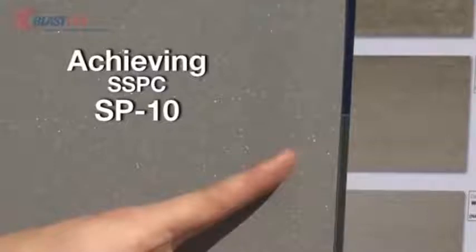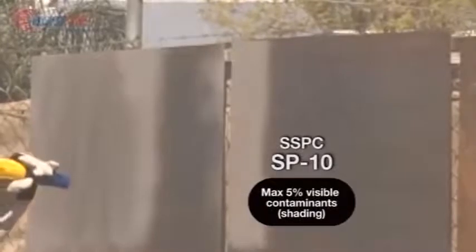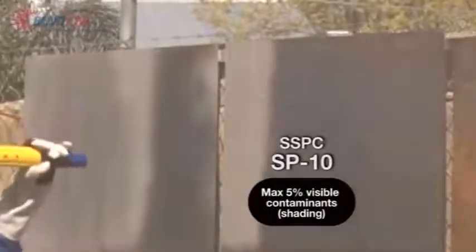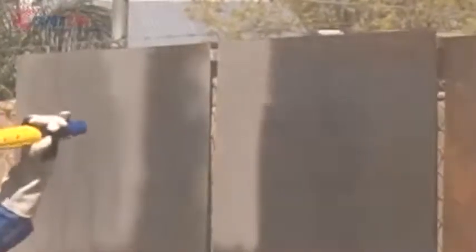How to achieve an SSPC SP10. The technical specification for this class of blast is a maximum of 5% visible contaminants or shading. When trying to achieve SP10, the operator is paying careful attention to overlapping his blast patterns. On the grade A steel, it is typically faster and better to use long strokes of the nozzle instead of going around in circles, as this will achieve a much more consistent blast.